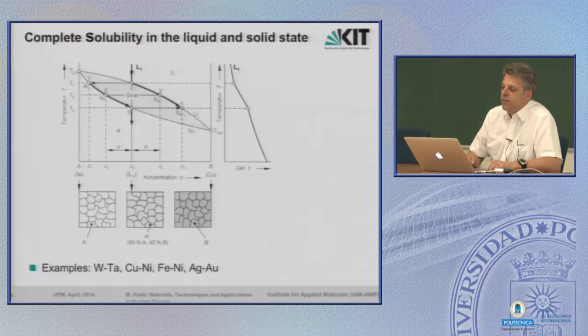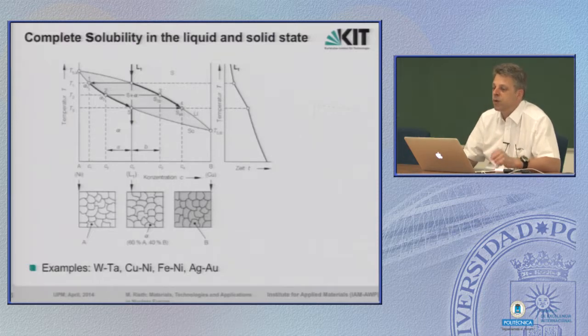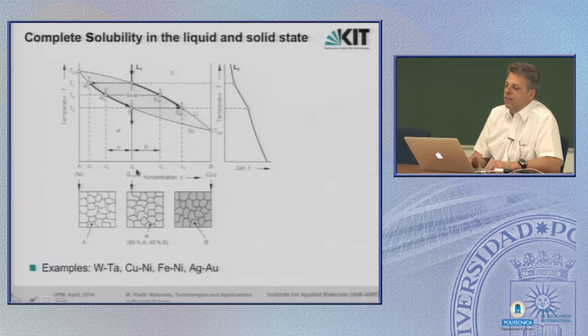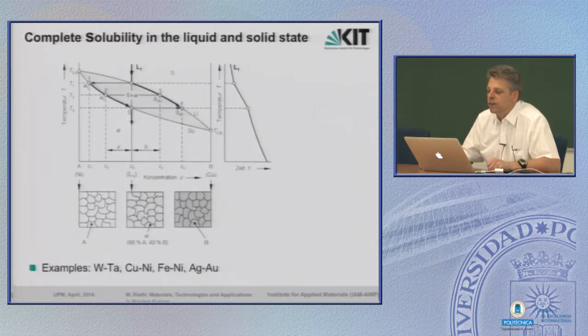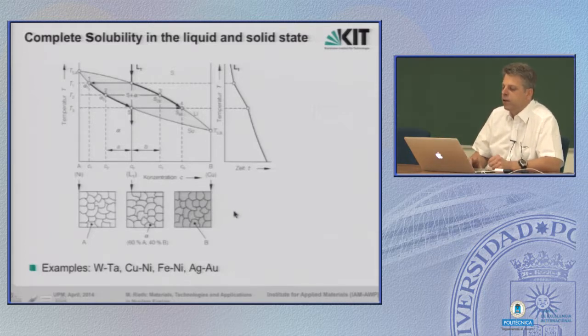So this is the case if two elements are completely soluble in the liquid as well as in the solid state. This means we start here from the liquid phase, cool down, then you see here a second phase depending on temperature and concentration, where both elements mix. In this phase they produce a solid state, that's the mixture of A and B component. They form a solid solute, that's a crystal lattice, a solid lattice with a mixture of both types of atoms, and the rest is still in liquid phase. If you cool further down, what you end with is the so-called alpha phase, that's the mixture of both in solid state. That's quite simple, there are a lot of examples: tungsten tantalum, copper nickel, iron nickel, and silver gold.